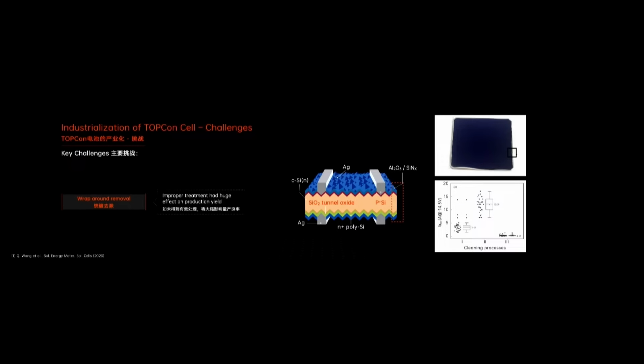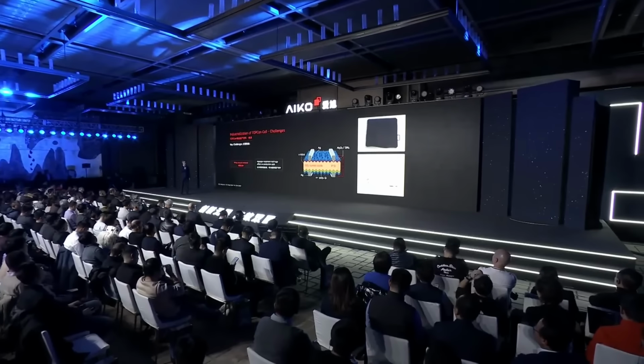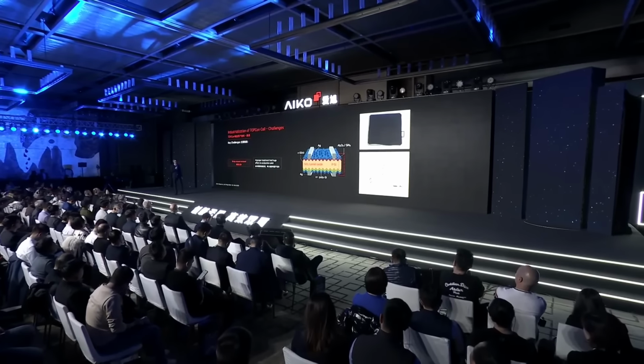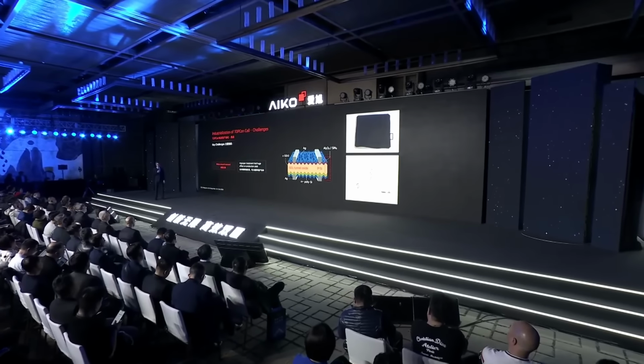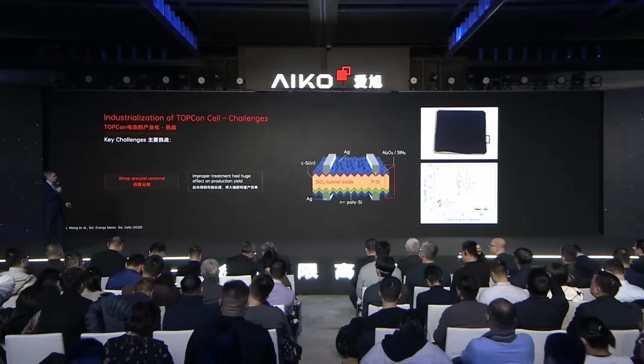Now I would like to talk a bit more in detail about a few challenges during the development. So when going to large area, then especially with LPCVD deposition, you have to deal with the wraparound of the layers, so that there is a deposition at the edges, but also on the front emitter. And you have to carefully remove the wraparound without over-etching the front emitter. If you, let's say, etch too little, then what happens is that you basically create, in the worst case, a shunt, or as you can see from the graph on the right-hand side, you have a very high leakage, a very conductive leakage path at the edge, which gives you very high reverse currents. So such cells, although they might have a relatively decent efficiency, cannot be brought into the module, because then you would have hotspot problems.